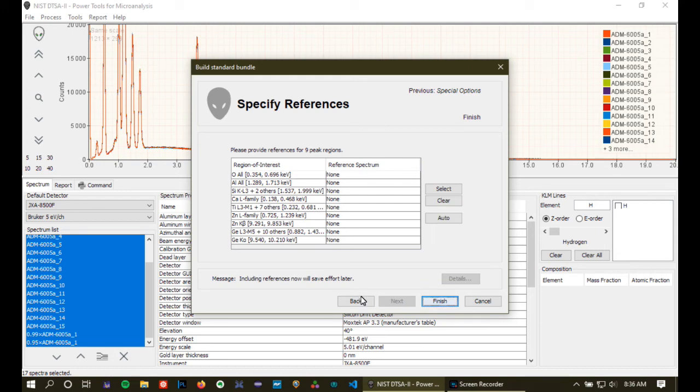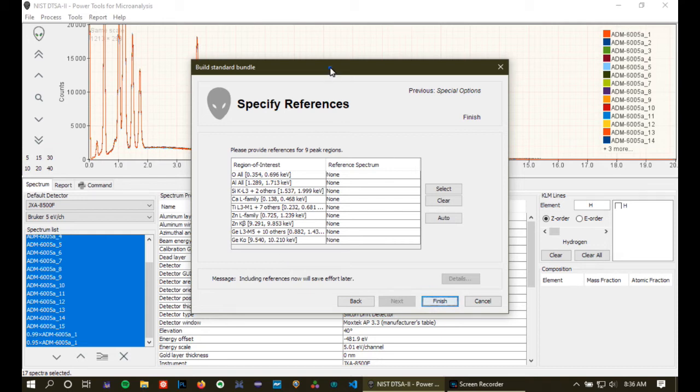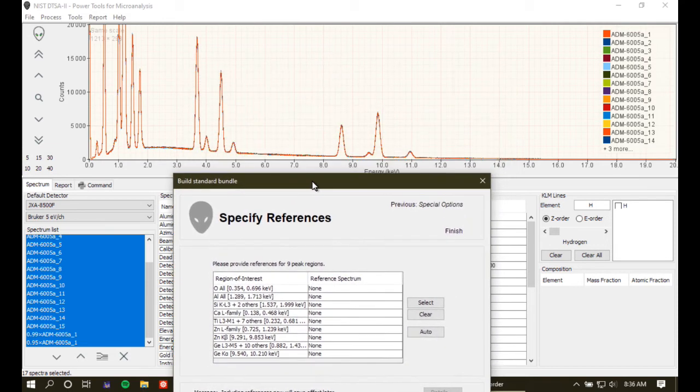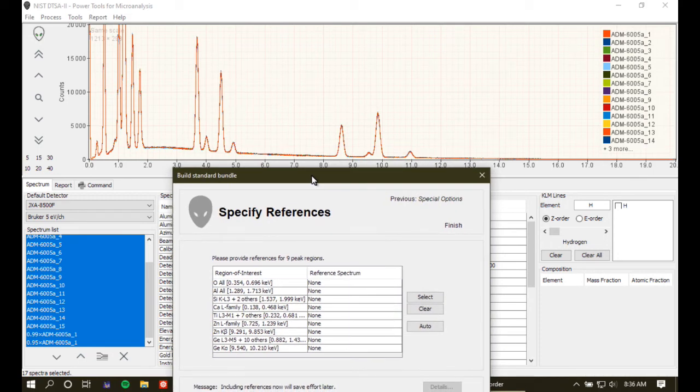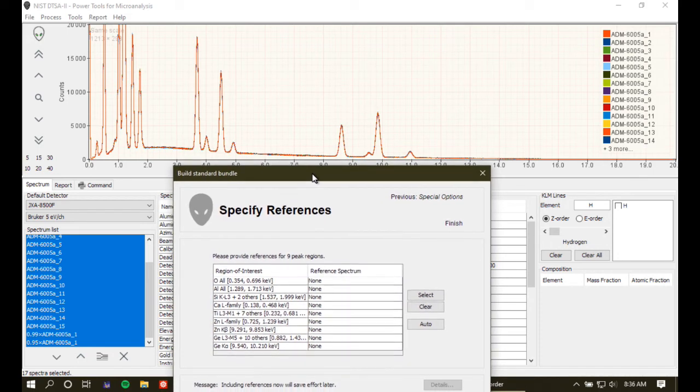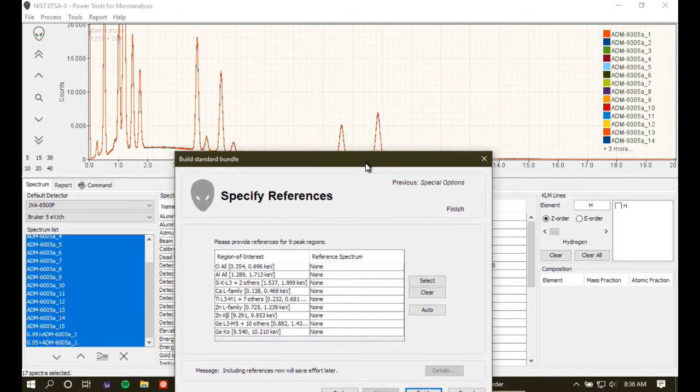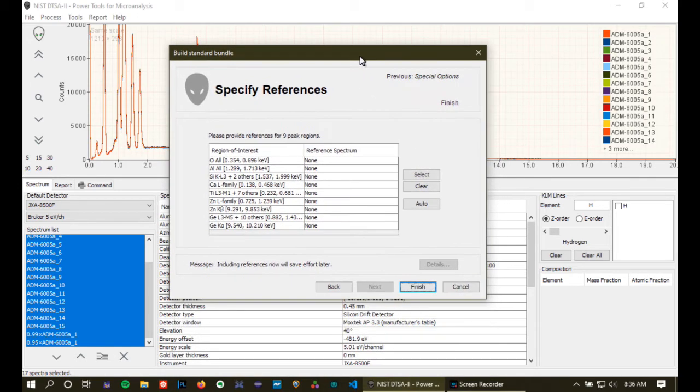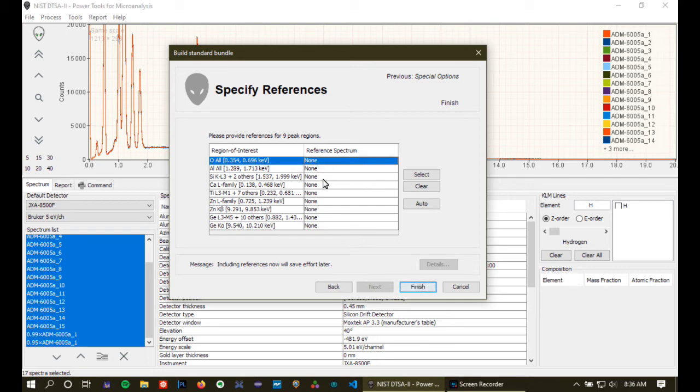Okay, so we get to this page here. And this page here tells us basically what references are required. So if we look at the spectra, it isn't clear that there are a lot of interferences, but there are. Because in the low energies, the peaks are too close to each other, and we can't separate them. In the high energies, you can see that these peaks interfere. So we're going to need references to be able to fit those peaks cleanly. And so that's what we're going to do. We're going to provide them.